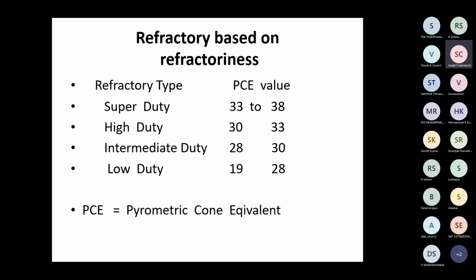Pyrometric cone equivalent: you have to prepare a cone. You heat this cone, and the cone will melt and bend and touch the base. This is the method of finding out the pyrometric cone equivalent. The temperature is very critical. So refractoriness is the temperature by which we can find out whether it will be softened or melted or something like that.